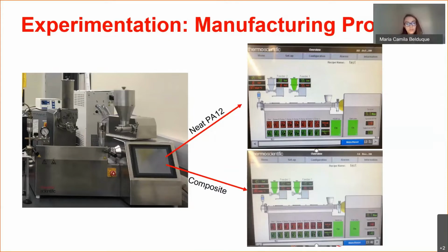Again, we use the single screw to feed the matrix material, which is PA12, and when it reaches the melting state, the magnetic particles are added using a mini twin feeder, which has two screws. We also increase the temperature when extruding the composite to reduce the pressure in the die.